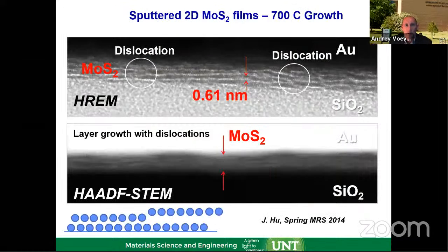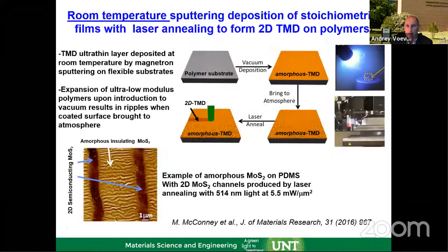Apology for that. But if you grow this, we will produce those few monolayers of thickness here. This has some interactions in the grain boundaries, which slow down the charge transfer, which for high-speed computing is of course a problem. But if you're doing sensor applications, you're not concerned about how fast the charges are moving in here, so that's just not a problem at all. But the advantage is that we can start dropping the temperature down.